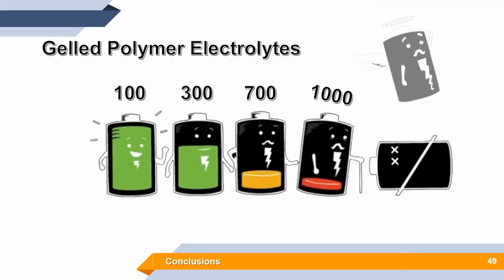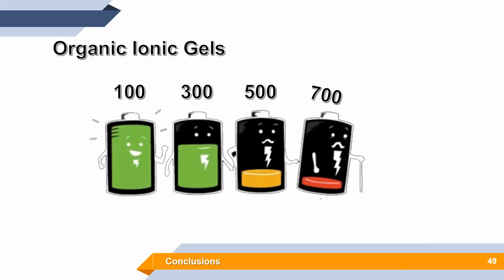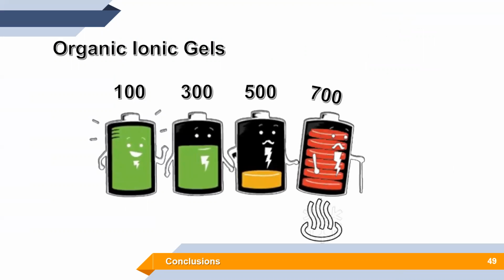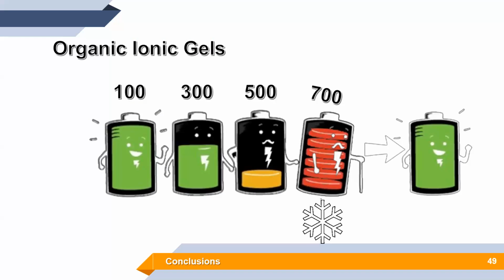So when we use the standard batteries with polymer electrolytes, after, let's say, 1,000 or more recharge cycles, the system becomes degraded, and what we can do is only dispose of it. In case of organic ionic gels, of course, this process is faster because the driving forces and the physical interactions which create the gel phase are more fragile. So the system is used up faster, but it is easy to recover its primary properties just by appropriate thermal treatment. So in the end, we end up with a new battery, but in the old package. So we can use the same battery again and again.